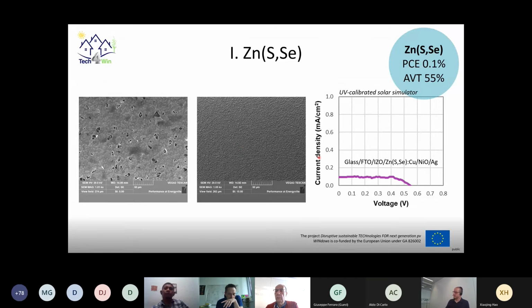Still, where are we? At the right, you see a first JV result for a thick zinc sulfide selenide layer. And you also see here copper doped. Indeed, if we make pure zinc sulfide selenide, then the conductivity is quite low. So typically we are even doping the material with another element, like for example here copper, which is increasing the conductivity at least threefold.